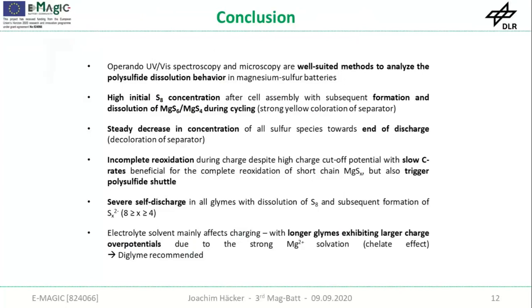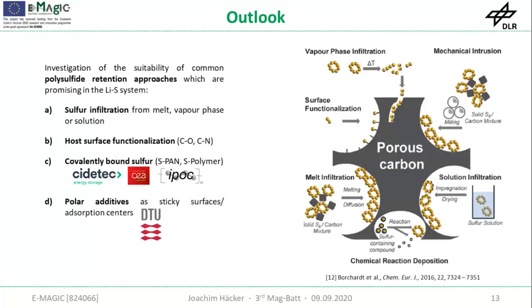Severe self-discharge was observed in all glymes, unfortunately, with the dissolution of S8 in the beginning and the subsequent formation of shorter polysulfides. And from the glyme family, diglyme is recommended due to the best compromise of solvation, viscosity, and volatility.